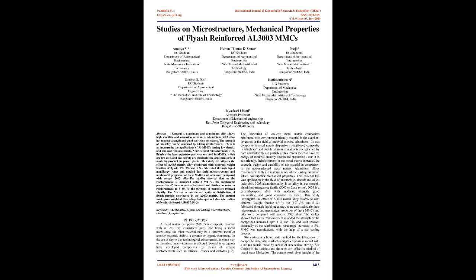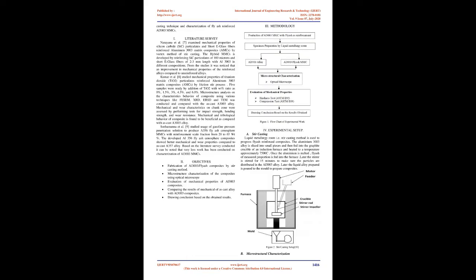This study investigates the effect of a 3003 matrix alloy reinforced with different weight fractions of Flyash, 1%, 3% and 5%, fabricated through the liquid metallurgy route and studied for the microstructure and mechanical properties of these MMCs, and later compared with as-cast 3003 alloy. The studies showed that as the reinforcement is added, the strength of the composites increased up to 1% and 3%, and later reduced drastically as the reinforcement percentage increased to 5%.